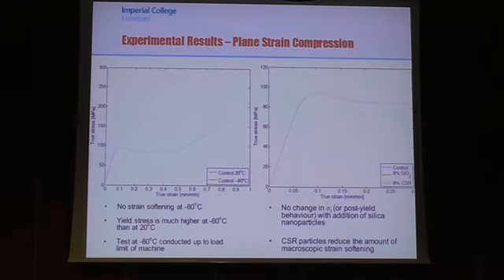And on the left-hand side here, I have an example of a 20 degrees, the blue line. So we see initial elastic region, followed by yield, followed by a strain softening region. This here was when the sample actually cracked a little, so you get a slight loss of constraint. But then the sample strain hardens, and then you get final ultimate failure. So we can record the true strain to failure.